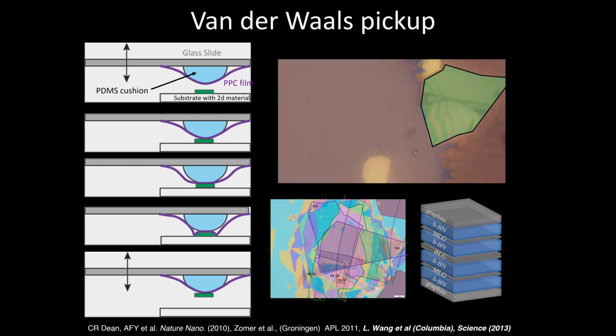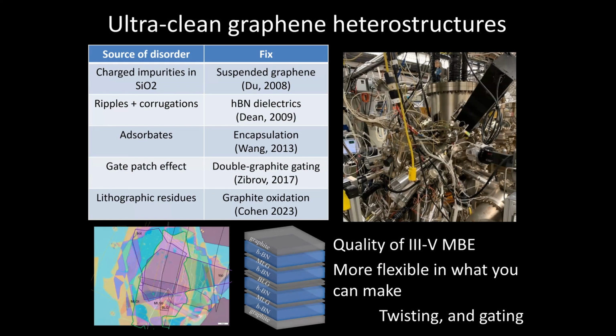Certainly, a UCSB undergrad, a Caltech undergrad, could probably do it in a couple of days. And the sort of remarkable thing is that, through a succession of improvements to this process, you can now make these two-dimensional electron systems, even though you're doing this basically with sticky tape and air, with the same type of quality as you get in a $1 million molecular beam epitaxy system with III-V semiconductors, which is an extremely well controlled and well studied system.